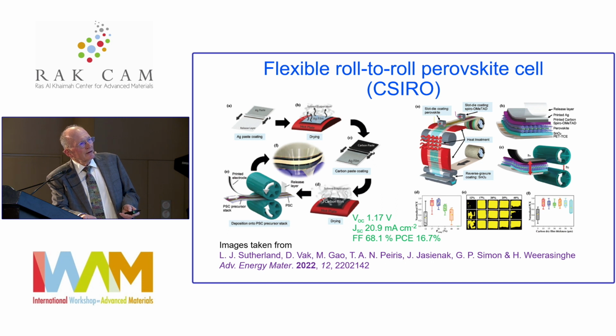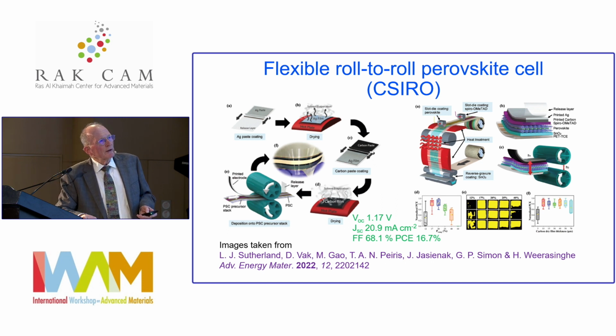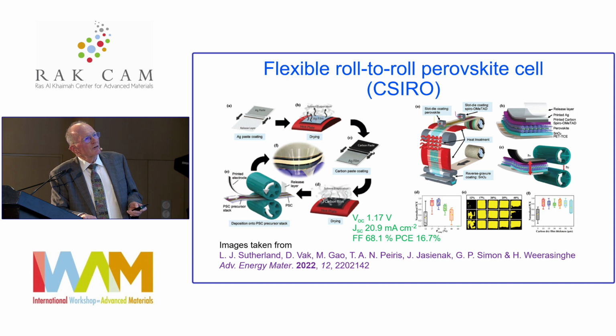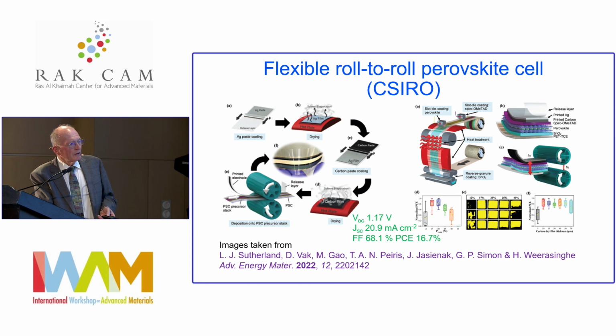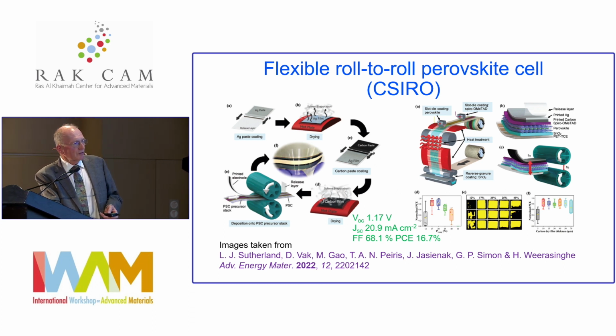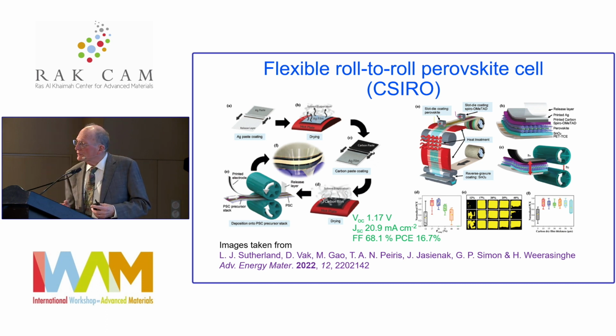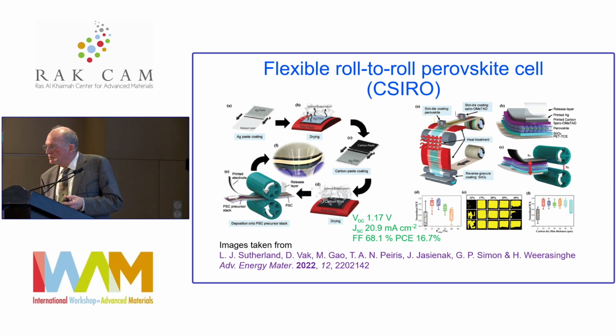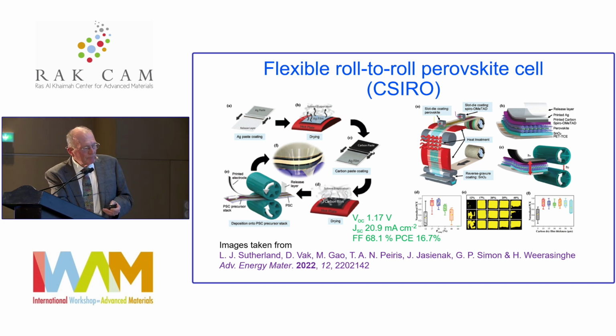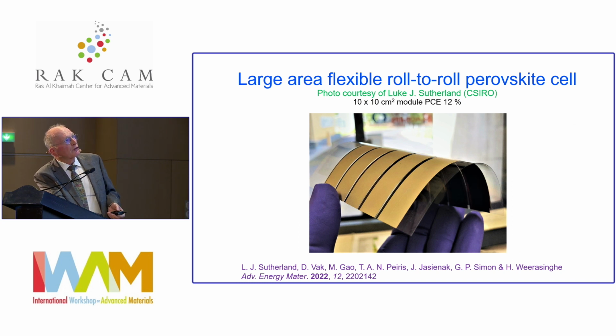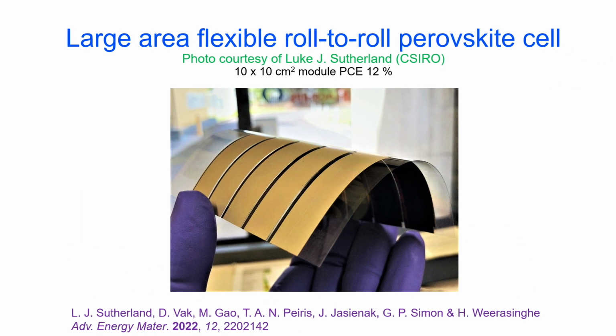And then this calender press assembly of the top electrode gives you a device which has this configuration with the printed silver on top. And there they achieved, on a small device, an efficiency of 16.7%. And you see, there it is, the limiting factor is again this fill factor. And I think that's going to be the thing that printing deposition, or deposition from solution, has to overcome. And they produced a 10 by 10 square centimeter module with a 12% efficiency. And I think these have been validated. So I think that's really quite an impressive result.